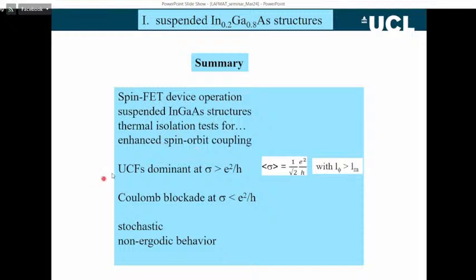In the suspended layers themselves, we have the universal conductance fluctuations at high conductance, and at low conductance, where the chemical potential has really dropped into the tail of the density of states, we see a Coulomb blockade effect coming in, and the system behaves as if it's stochastic. So we know we're going to get this behavior. We just can't predict when or how. So the system goes over to being stochastic. It's also non-ergodic, but it's not non-ergodic because of this zero conductance, zero thermal conductance behavior.